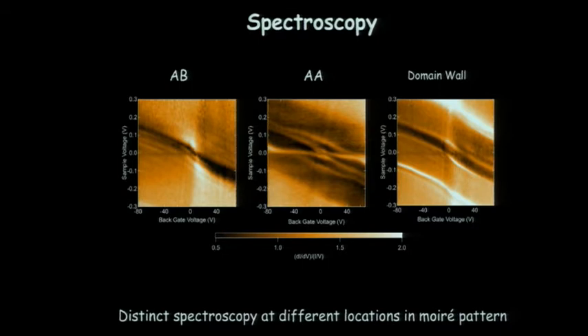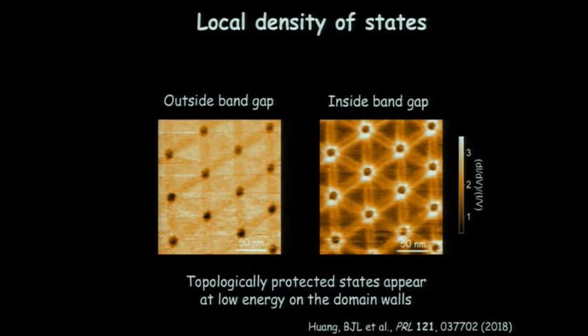To look at this a little bit more clearly, instead of just taking spectroscopy at fixed locations, we mapped local density of states. We took local density of states measurements inside and outside of the band gap. Outside of the band gap, at high energy, everything is conducting. You see essentially a uniform density of states on the regions other than the AA sites, so on the AB regions and the domain walls.